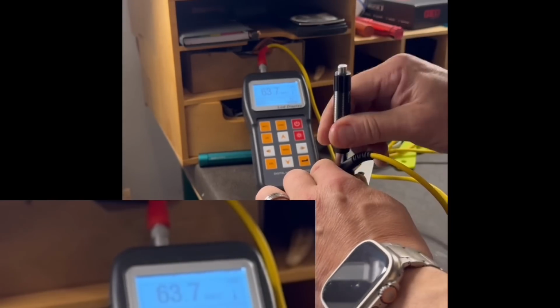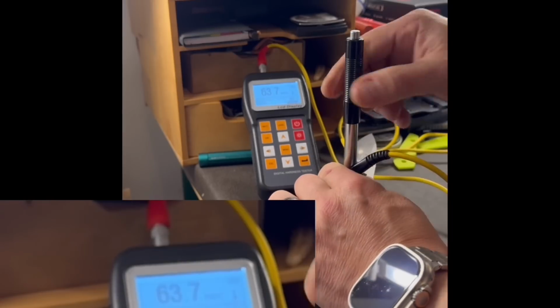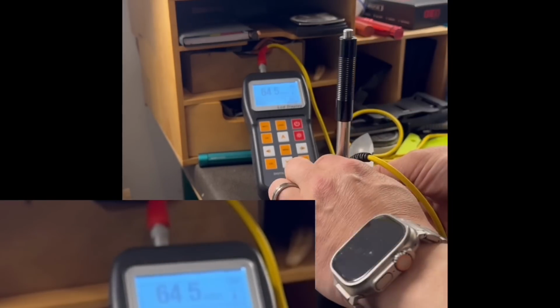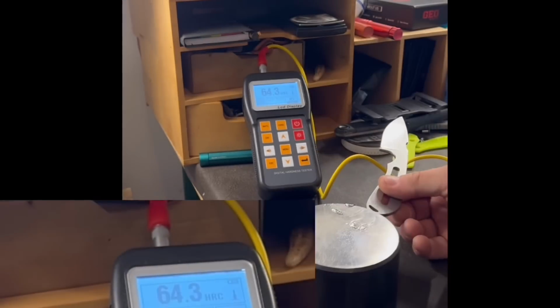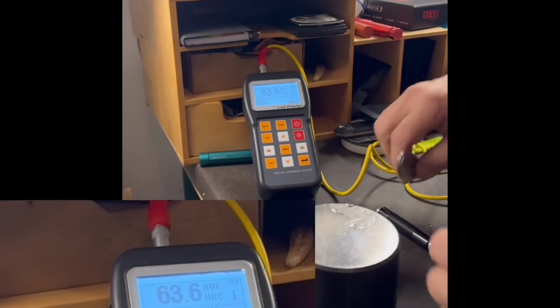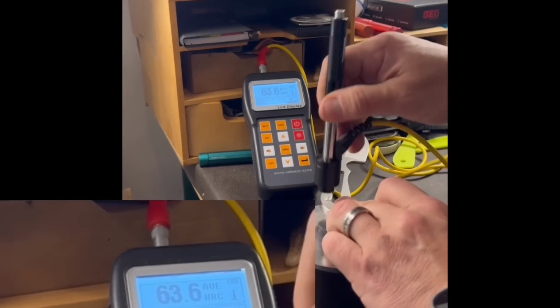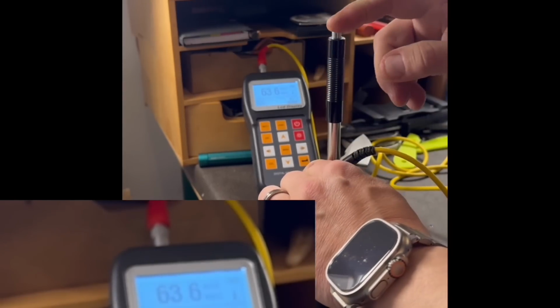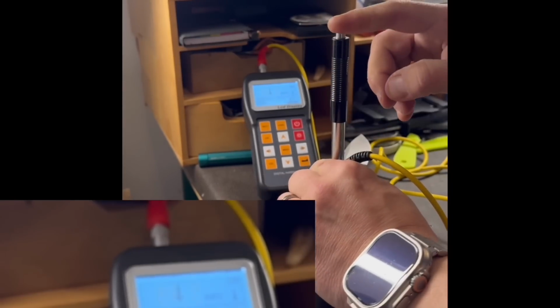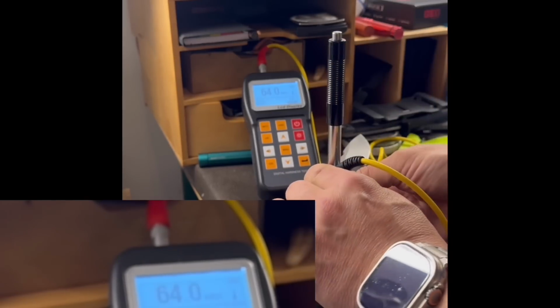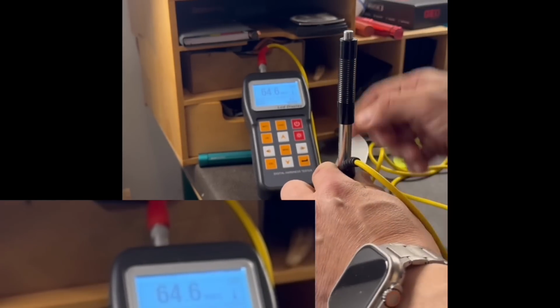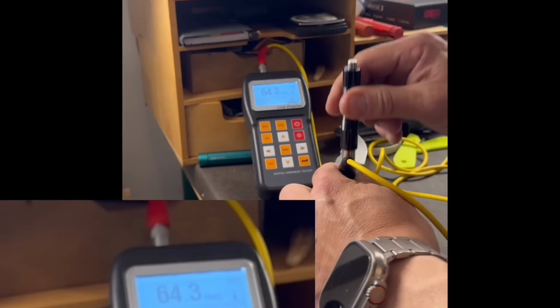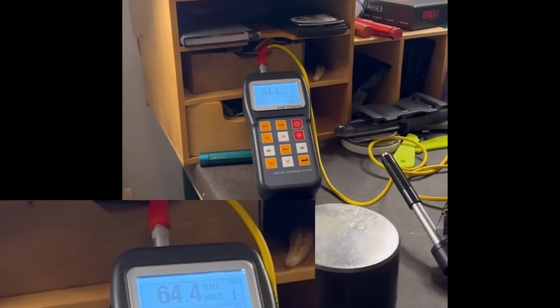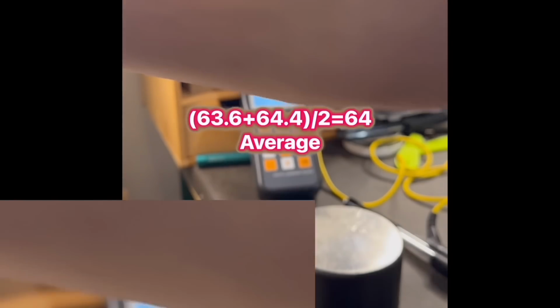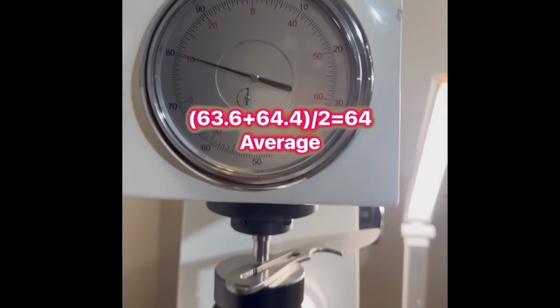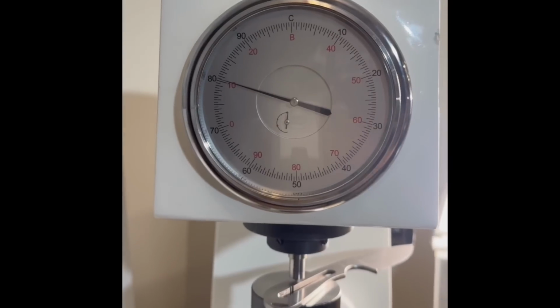Let's see what kind of average we will get over the 5 strikes. The computer interprets the return velocity of the rebounding probe to estimate the hardness. And this time the average is at 63.6 HRC. Flipping the blade over, I'm going to do another 5 strikes on the opposite side. A typical Leeb tester has repeatability of plus or minus 8 Leeb points or plus or minus 0.5 HRC. That is why it's critical to look at the average result and not at each individual strike, which in this case is 64.4 HRC. And therefore, this blade measures on the Leeb at 64 plus or minus 0.5 HRC.